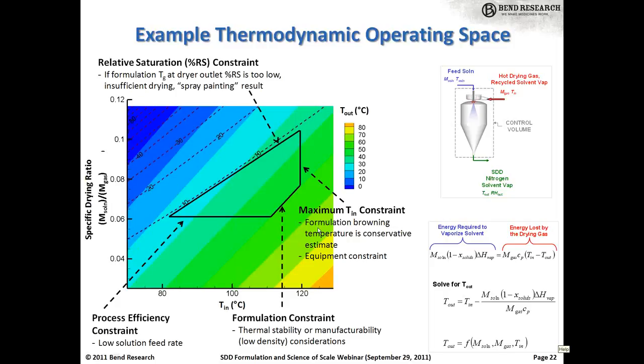Then within the plot, we're showing contours of constant outlet temperature, and also another calculated parameter, the lines of constant relative solvent saturation or wetness within the spray dryer. So as you move back to this blue corner in the back here, this ends up being your colder, wetter drying conditions. And you can start to bound the parameter space that you may be interested in running at. So we'll go through a few of those.